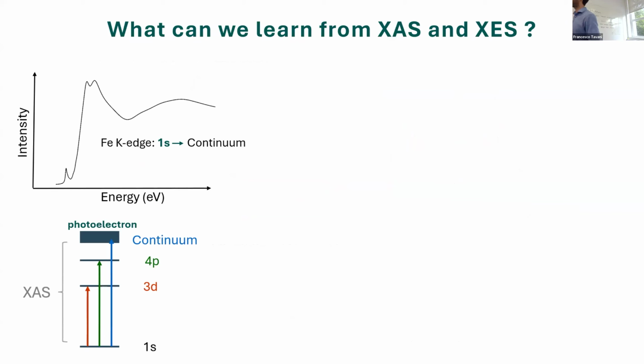In the case of XAS, this is just an example I'm showing here. This is an iron K edge. We are considering transitions from the 1s state of iron into the continuum, and this will be the energy required to eject the 1s electron as a photoelectron. And then at that point, there will be all sorts of multiple scattering effects that give rise to a modulation of the cross-section.